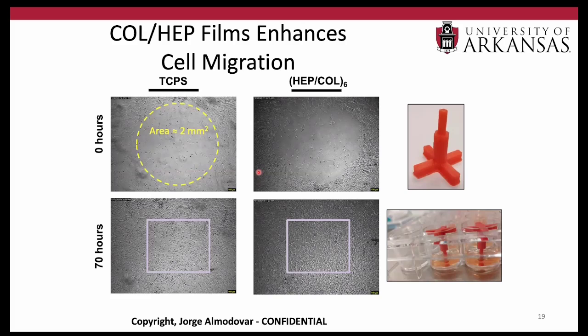All right, so we did another study to see what was happening. In this study, we did a migration assay where my student 3D printed this barrier, where this tip here would go at the bottom of the well. You would seed cells all around that tip, and the cells would attach and grow, but they would not enter the area where the tip is in contact with the well until you remove it. Once you remove that, we can observe over time how the cells invade that empty area.